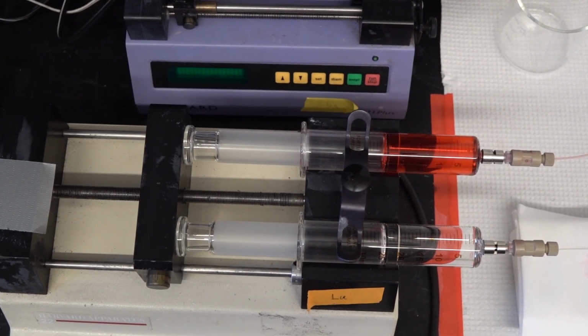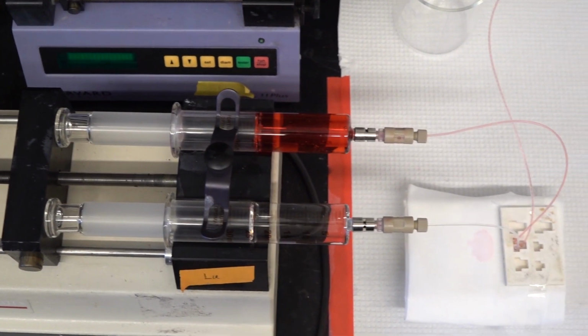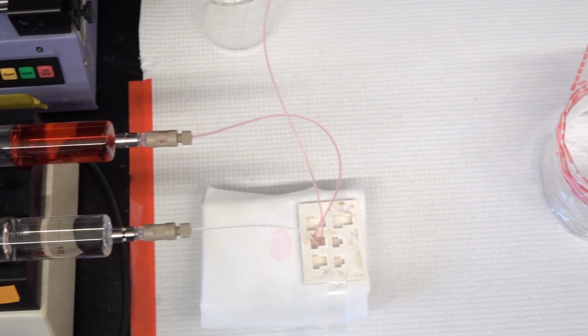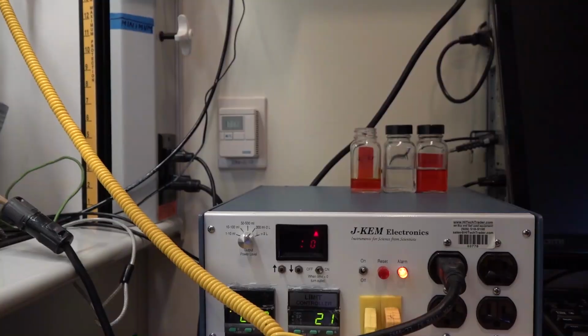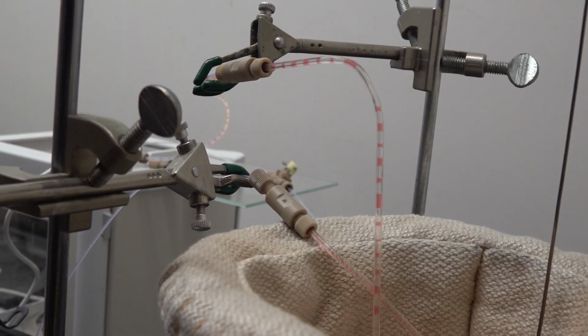Hi, I'm Emily Roberts, and I'm a graduate student at the University of Southern California. I work for Professor Richard Brutchey in the chemistry department, and in collaboration with Professor Noah Malmstead and graduate student Lu Wang, we work on developing high-temperature reactors for the synthesis of nanoparticle catalysts. In a typical molybdenum carbide synthesis, we prepare our precursor solutions and then put them into syringes. The syringes are then placed into syringe pumps and flowed at different flow rates depending on the desired residence time. Upon entering the reactor, it is heated to a desired temperature, in this case upwards of 300 degrees, and this is where the reaction takes place.